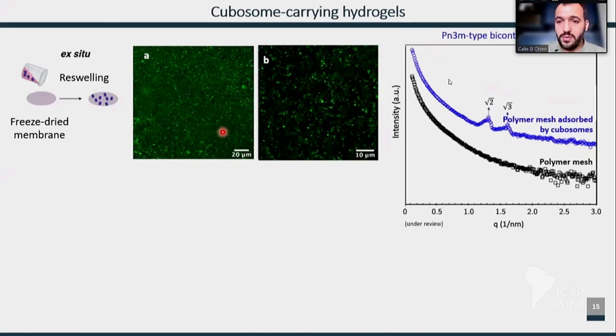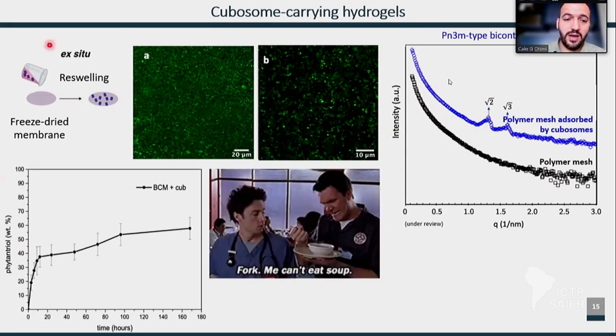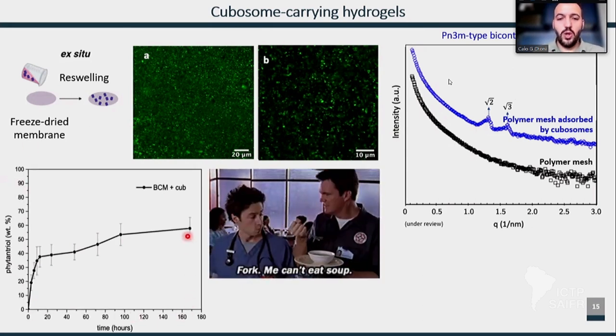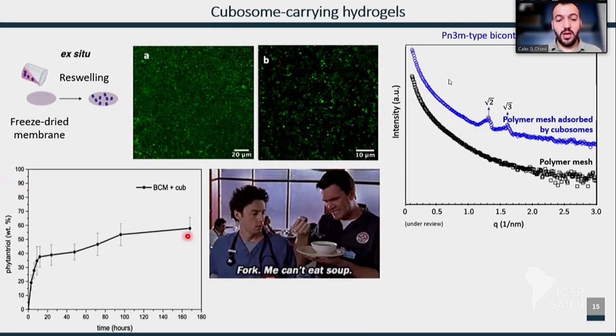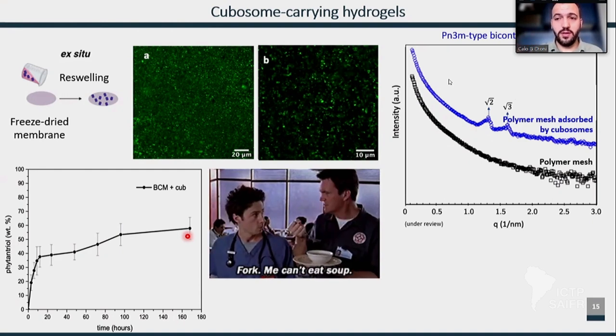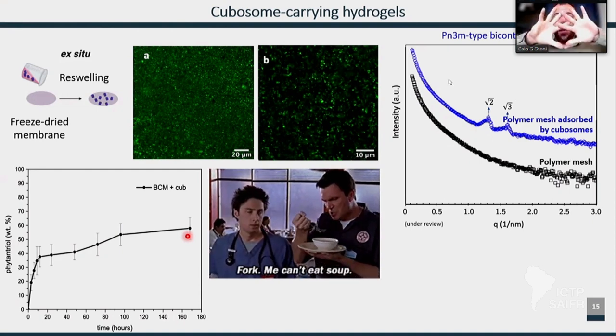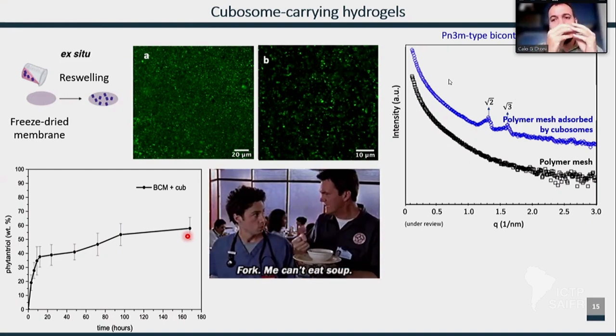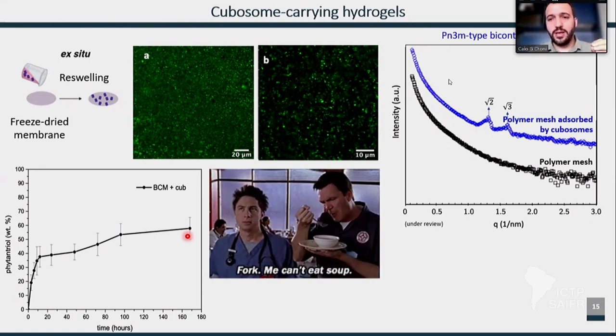But you can really see from SAXS that you have the pristine mesh and the typical cubic phase of cubosome when you have the incorporation, but you have a lot of leaching. You lose a lot of cubosome because what we are trying to do is to have soup with a fork, right? So you have a big mesh and tiny particles, so they will eventually run away quickly.